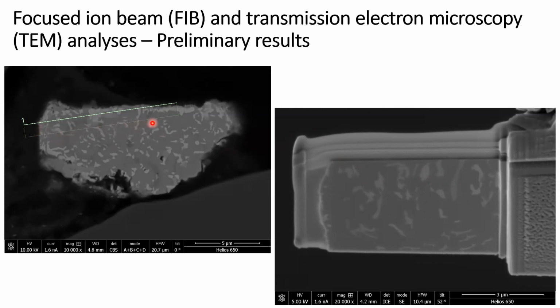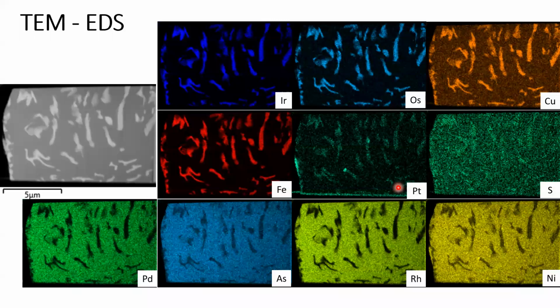This is the section that was cut in order to obtain this lamella. And here I have TEM EDS analysis. And this is an elemental mapping and shows that the matrix of this lamella is mainly made of palladium, arsenic, rhodium, and nickel. And the intergrowths are made of iridium, osmium, copper, iron, and some of them have some platinum and small amounts of sulfur.